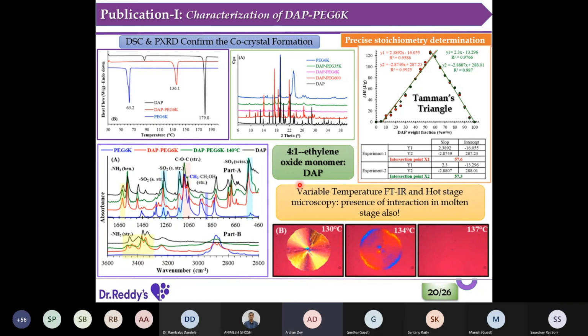We also did the IR to confirm that, and that makes sure that the amine groups and the sulfur dioxide stretchings have changed, which indicates some hydrogen bonding interactions happened. Then another extra step we did: hot stage microscopy and also variable temperature IR. That's giving a bit of uniqueness. In the molten stage, even the hydrogen bonding interaction shows no change. That indicates that in the molten stage also these materials are still co-associated.